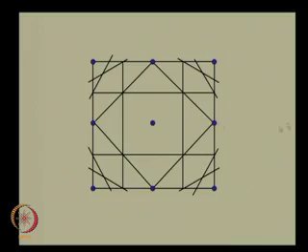So, having got this array of perpendicular bisectors to lines joining the origin to all the neighbors around the central lattice point, we can now identify Brillouin zones based on the definition we have given for Brillouin zones, which is basically that the first Brillouin zone is the region in space around this point which can be reached from this point without crossing a single Bragg plane, and therefore that would be the region that is identified here. Okay, so, this region around this point is therefore the first Brillouin zone.